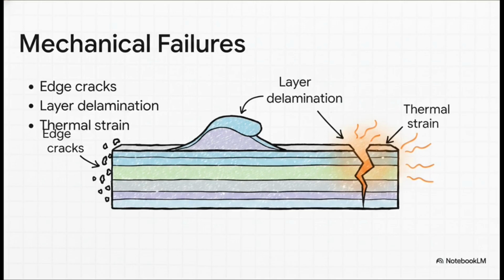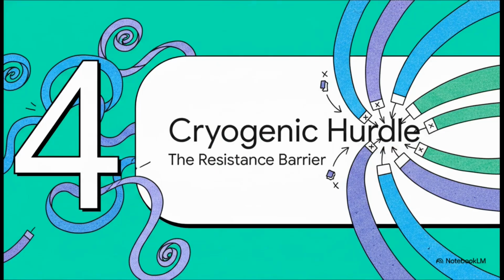And when you actually put these tapes into real-world high-field magnets, the massive Lorentz forces can cause the layers to literally peel apart and delaminate. Or, say a localized hotspot forms during a quench, the thermal expansion will crack that brittle ceramic layer right down the middle, causing permanent damage. It's a real nightmare.